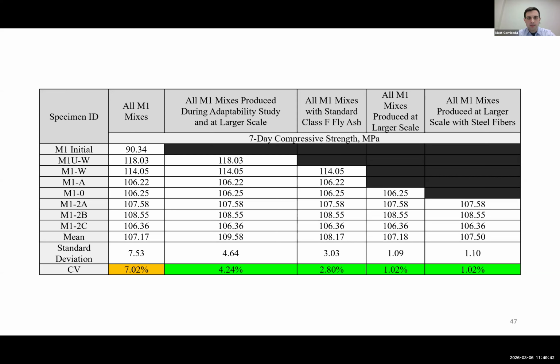When we just do it at the stuff that was done in our lab, the initial one was done at UIUC. When we look at just everything done at IIT, it was reduced to 4%. When we look at everything that includes just the standard Class F fly ash, it goes down to 2.8%, as opposed to the U one, which was the sieved version. If we go then to just the mixes produced at the larger scale with the 3x6 specimens, we're at 1% COV. And we get 1% again if we look at the variation with those that were produced with steel fibers only. So the COVs here are actually really good across all these slight variations to get a standard characteristic average value without much deviation for all these different mixes at different categories here.